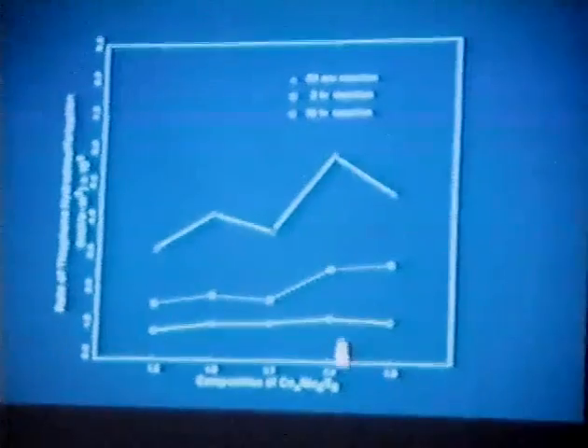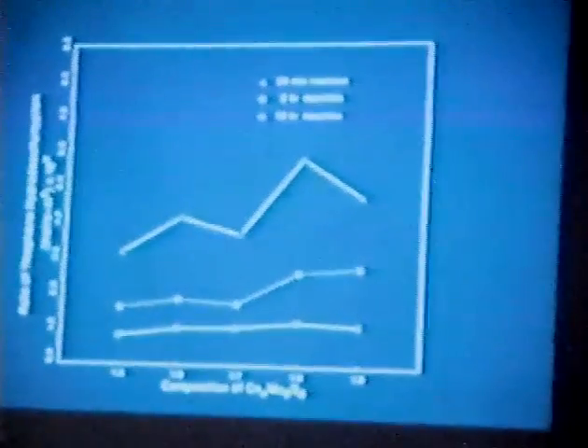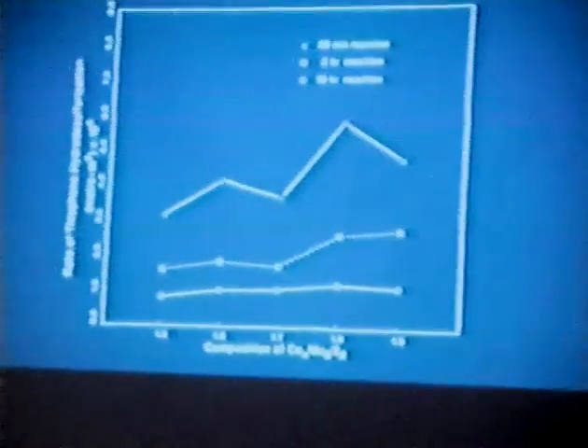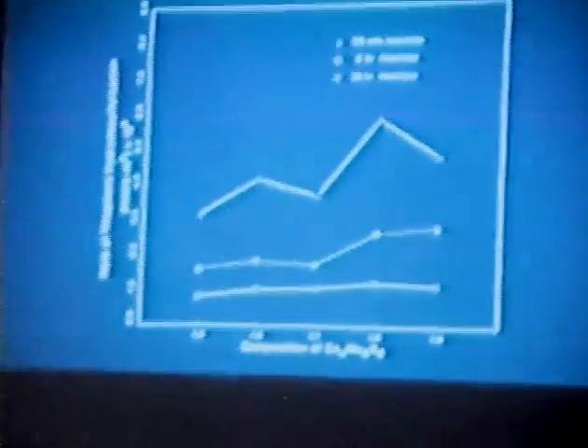And for some other compounds, although these appear to be rather stable, other compounds like cobalt, again there's some influence here of the composition, the amount of cobalt you have in the system. And this is also dependent a little bit on how long you have the material in the reactor. But again, this is a phase that was not particularly stable.